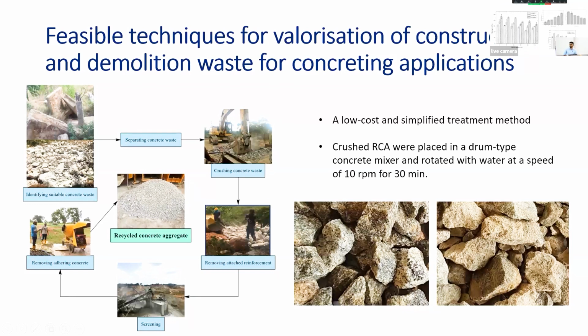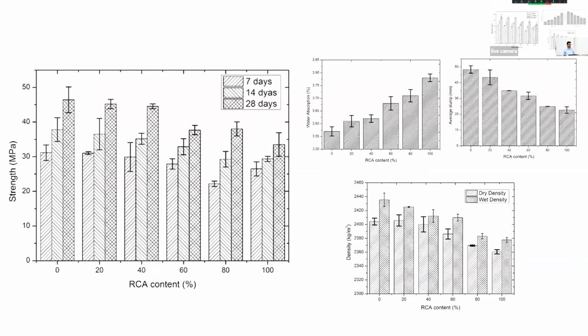So then these are some findings about the concrete that they have developed, and they have compared the concrete properties with the normal concrete with normal aggregates. This shows only selected properties: strength, water absorption, slump, densities. As you can see in the strength variation, we have about a 40% chance to replace the normal aggregates using these recycled aggregates, which can be developed using normal construction techniques and the normal facilities which are available in our normal industry.